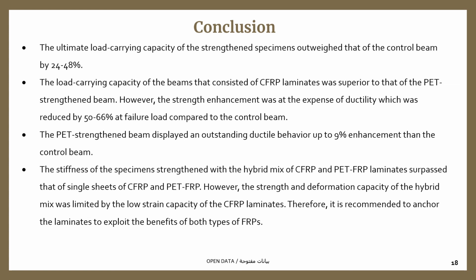The stiffness of the specimen strengthened with the hybrid mix of CFRP and PET-FRP laminates surpassed that of a single sheet of CFRP or PET-FRP. However, the strength and deformation capacity of the hybrid mix was limited by the low strain capacity of the CFRP laminate. Therefore, it is recommended to anchor the laminates to exploit the benefits of both types of FRPs.